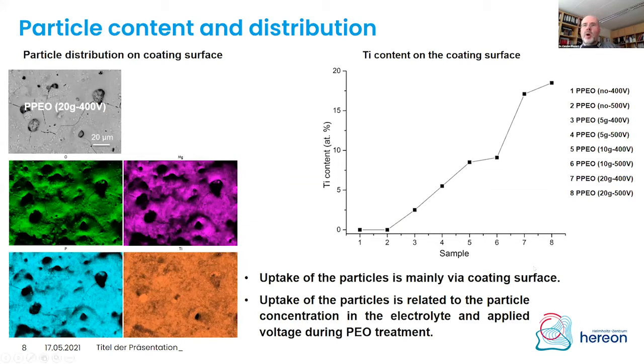So what our increasing amount of titanium dioxide additive is doing is that we can continuously increase the titanium content on our surface. And we can finally reach, with a 20 grams addition, regardless of whether it is running at 400 or 500 volts, up to 20% of titanium at the surface, but the titanium actually is an indication that we have mainly titanium dioxide. And this I would like to show you in the next slide.